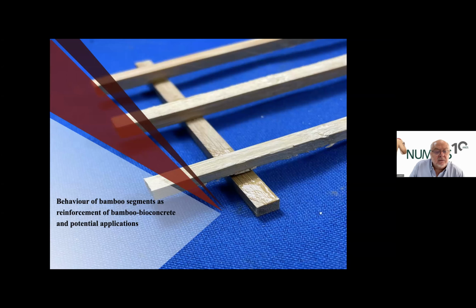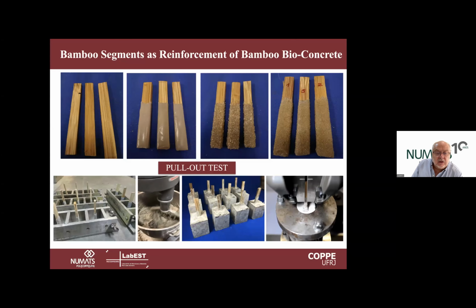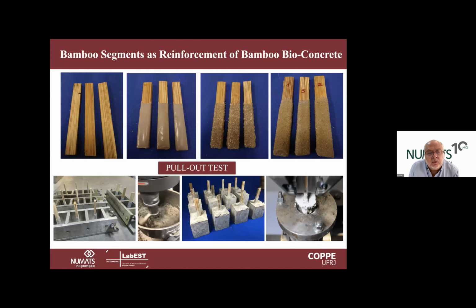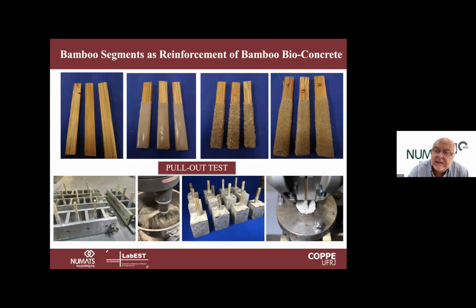Coming to the use of segments as reinforcement of bioconcrete now. So the first test we did was the bonding. Normally the pull out of these strips from the bioconcrete can be very low if we do not use any kind of polymeric coating. So we are using both a natural biopolymer as coating, and also a castor oil biopolymer, and also a commercial epoxy resin. And we also saw the influence of using sand, fine or coarse sand, to improve the roughness and the adhesion between the two materials. So it's a very critical part, the stress transfer.